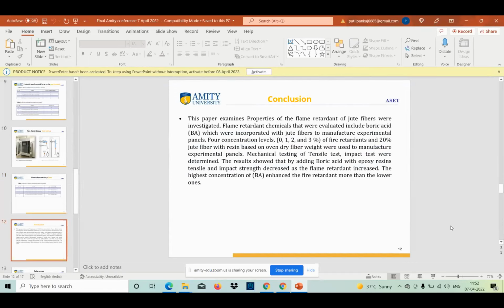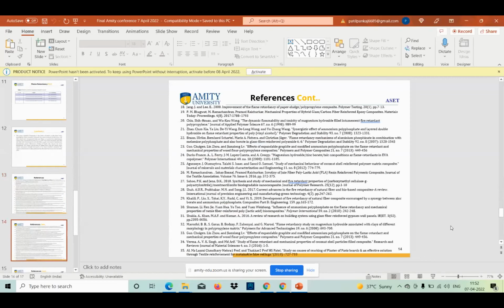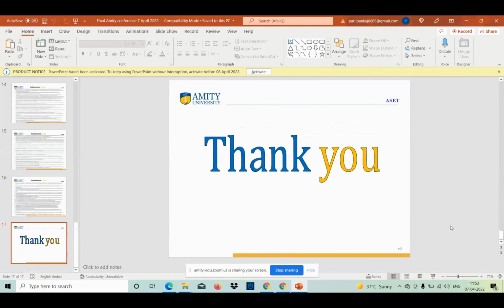The result shows that by adding boric acid to the epoxy resin, the tensile and impact test values decrease, while the flame retardancy increases. The highest concentrations of boric acid enhance the fire retardance more than the lower ones. So this is my conclusion for this paper. After that, these are the references for the paper.